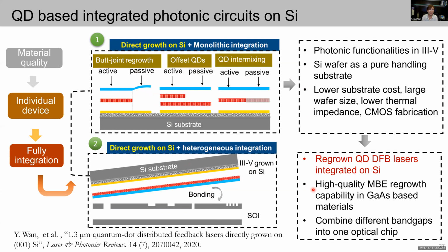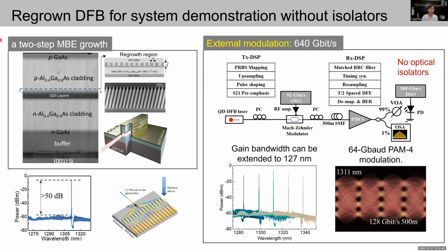And following this direction, we previously demonstrated a high-performance regrown DFB laser integrated on silicon substrate. And by realizing the very high quality and regrowth capability in GaAs-based materials, we can enable the possibility to spatially combine different band gaps into one optical chip. So here's the DFB laser growth structure, which is completed by two-step MBE growth. So the first growth is stopped at this 100 nanometer GaAs layer on top of the active layer, and then a uniform first order DFB grating was dry etched into the GaAs layer, and we carefully control the grating quality and the following regrowth surface treatment, so that we can get this very high quality regrowth of the rest part, and then we process into this deeply etched waveguide structure.